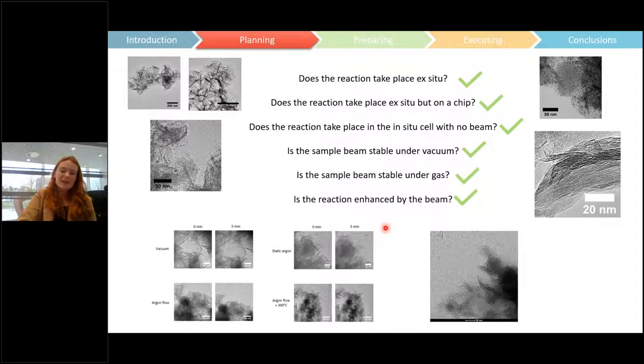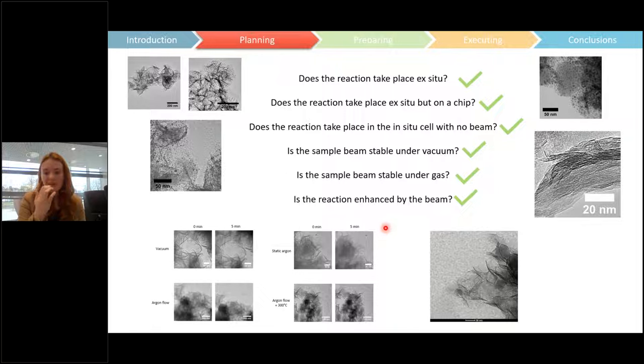And the last one is: is your reaction enhanced by the beam? As you saw before, when I played that video, by the time I'd refound my sample, my sample had reduced and we did have nanoparticles. This was very frustrating for me because it meant that my particle growth happened really, really fast. And here I was working very close to the temperature at which the particles should start growing ex situ, according to my ex situ experiments.